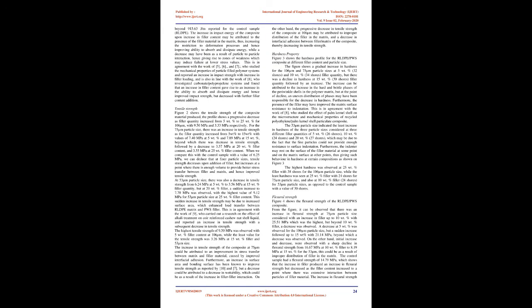When we compare this with the control sample with a value of 6.25 MPa, we can deduce that at finer particle sizes, tensile strength decreases upon addition of filler, but increases at a point where there is enough volume to provide better stress transfer between filler and matrix, and hence improved tensile strength. At 53 µm particle size, there was also a decrease in tensile strength from 6.24 MPa at 5 weight% to 3.56 MPa at 15 weight% filler quantity, but at 20 weight% filler, a sudden increase to 7.70 MPa was observed, with the highest value of 9.12 MPa for 53 µm particle size at 25 weight% filler content.